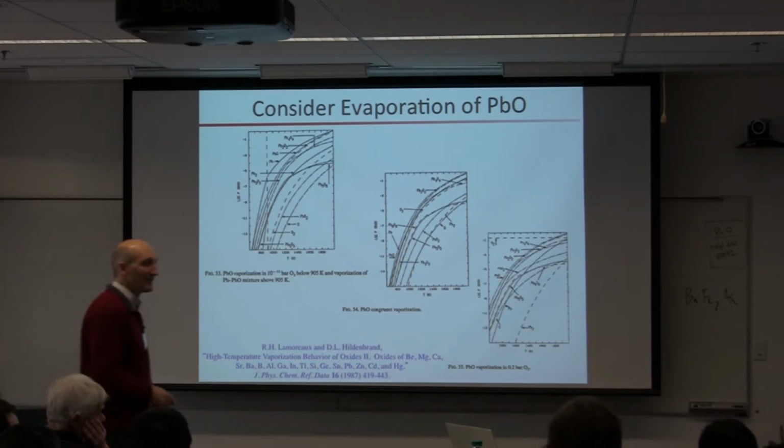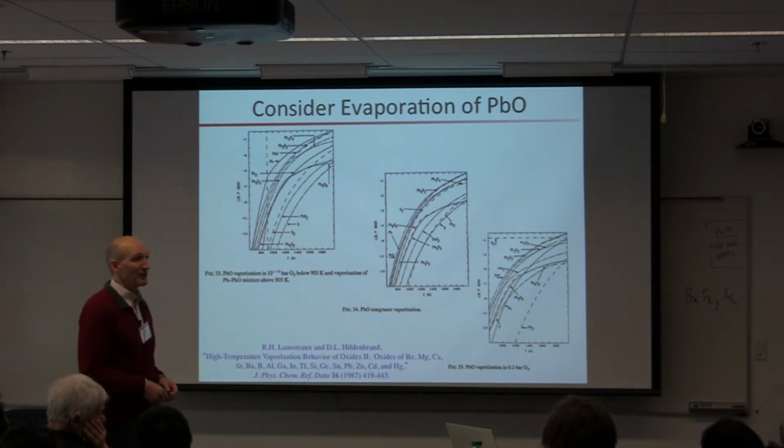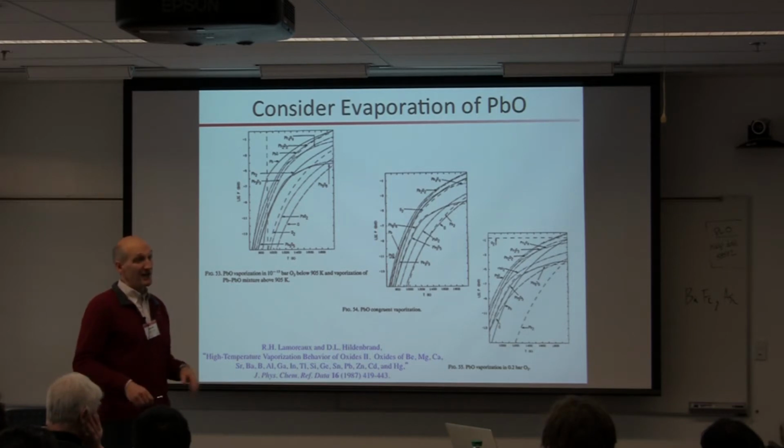Go ahead. How sensitive is it to the purity of the elements? Depends upon what you're making. For a lot of quantum materials, it's relatively insensitive. So in YBCO, you can put, not as much as a percent, but 0.1% of impurities, and you won't hurt Tc. Now that's incredibly high by semiconductor standards.